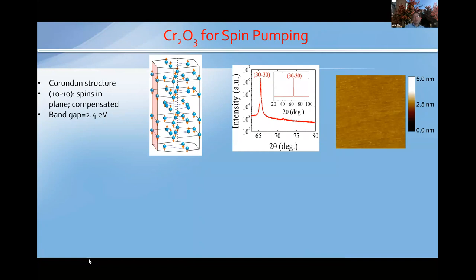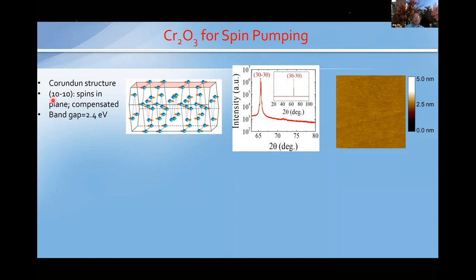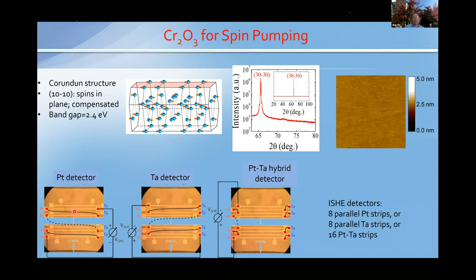The sample we use has an 10-10 surface, so the easy axis, the spin, is pointed in the plane. This XRD shows a well-oriented 10-10 orientation with reasonable surface smoothness. We use a set of platinum strips connected together, or tantalum strips connected together, strung together to form a really long detector. So we can actually have a huge boost in the inverse spin Hall signal from this type of configuration.